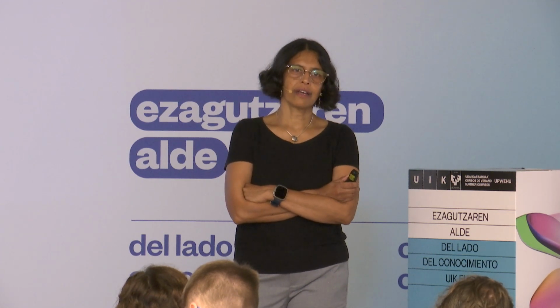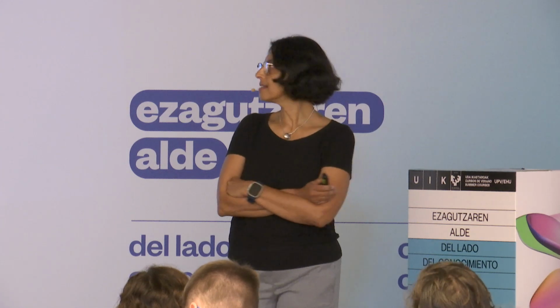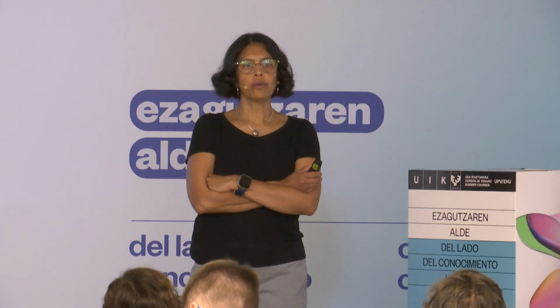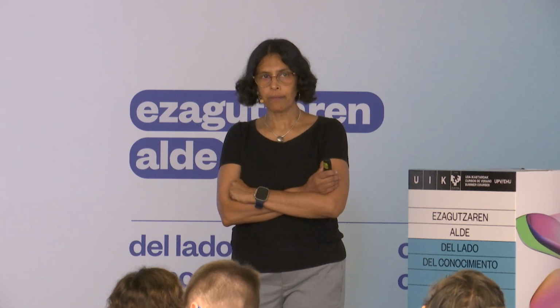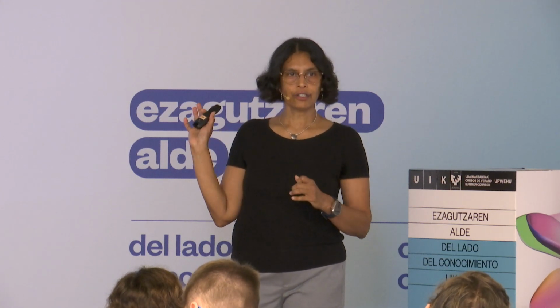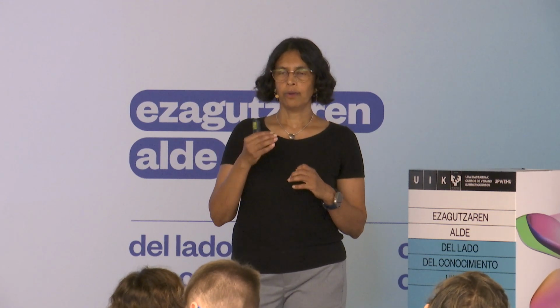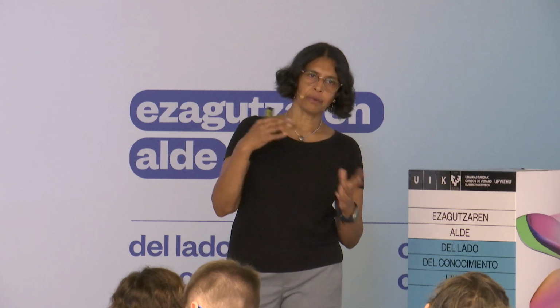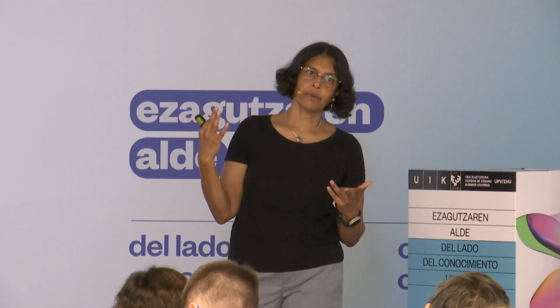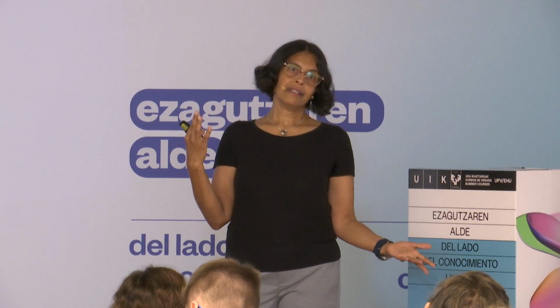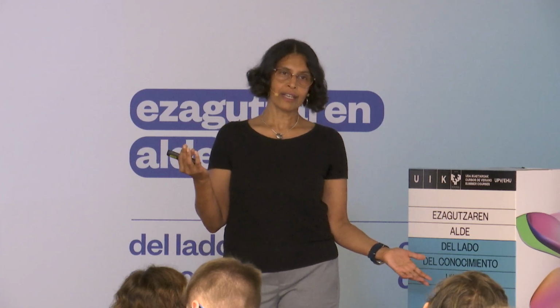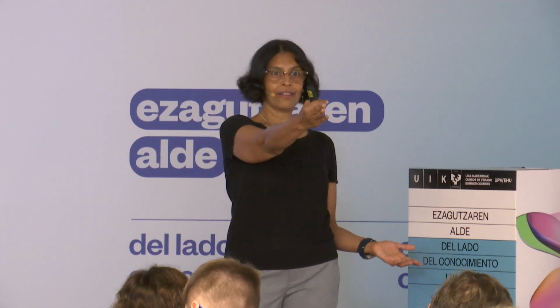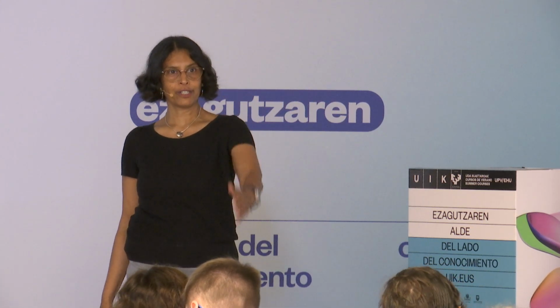Let's say you go to 2 Tesla and you have some order of the intensities. Then if you go back to 0, what happens? Does it keep that order, or does it switch it? And the thing is, we haven't done all of these experiments yet. We intend to do them. So go slowly from 0 to 2, see what happens, or even go higher. What happens at 0? Is there hysteresis, which I suspect is there, and that's another thing we could figure out by doing what you're saying.